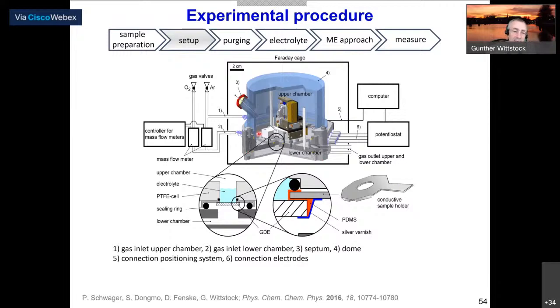So now how can we investigate this? We constructed a special measurement head for the SECM. You still see here the microelectrode. The sample is sandwiched here between O-rings. But now we have built around that system two gas reservoirs, an upper gas chamber and a lower gas chamber. They can be supplied with different gas mixtures, and the idea is to provide oxygen here and to remove oxygen here. The sample is then put in here with a special combination of PDMS and silver varnish for connecting.